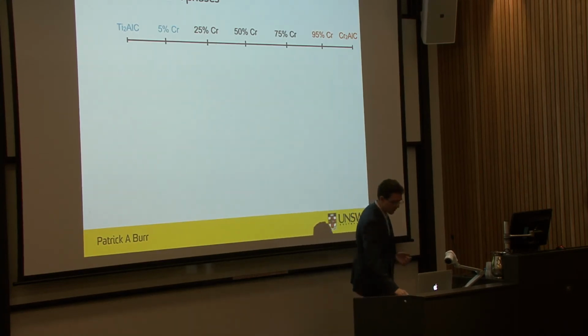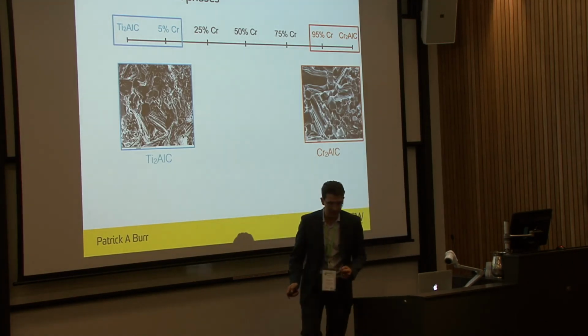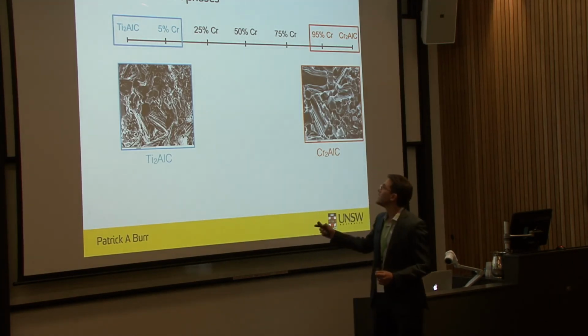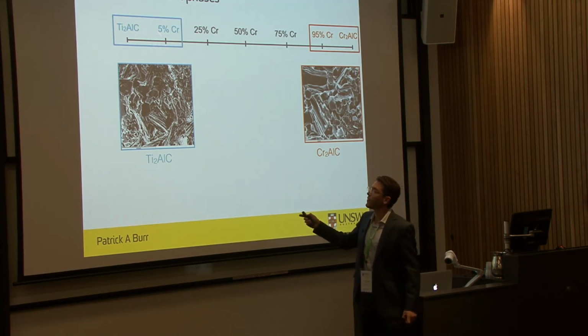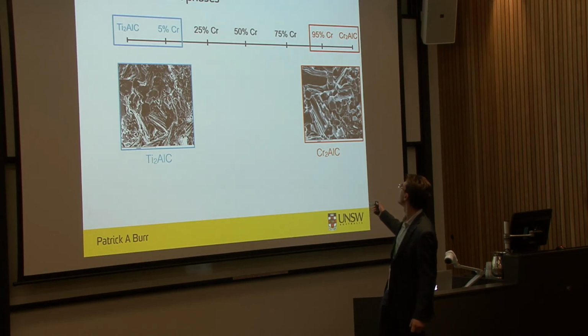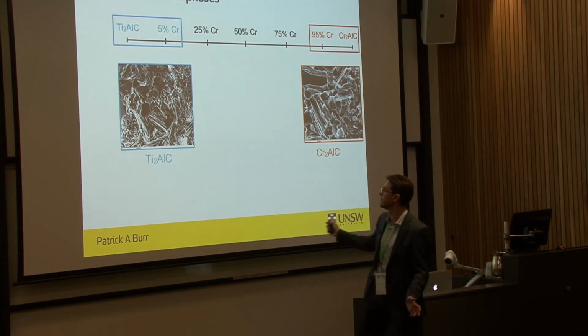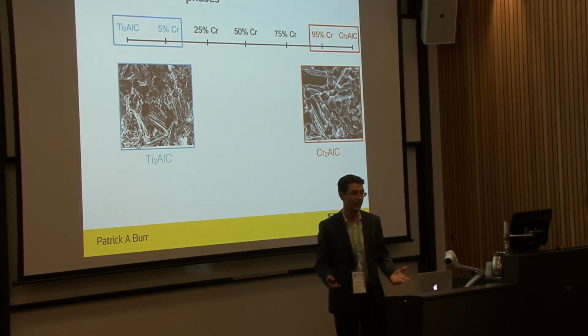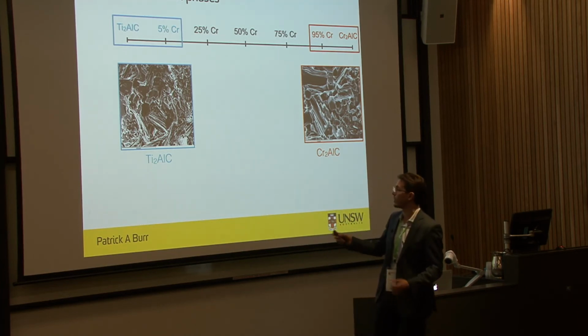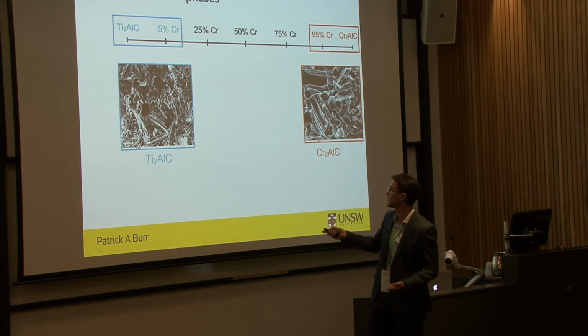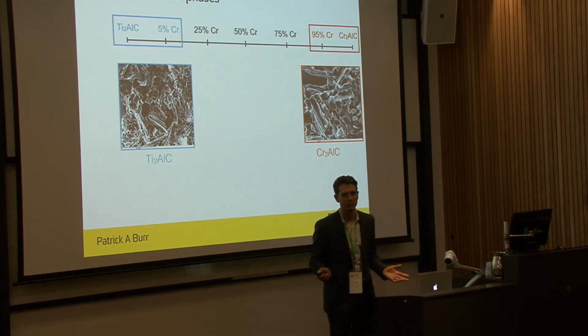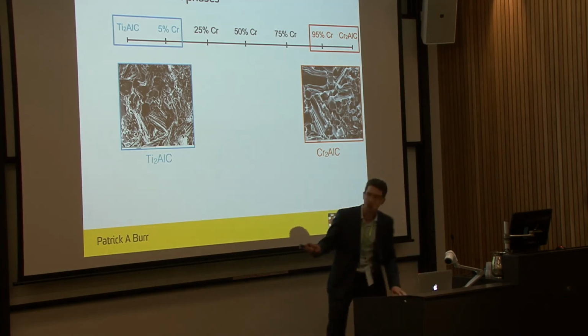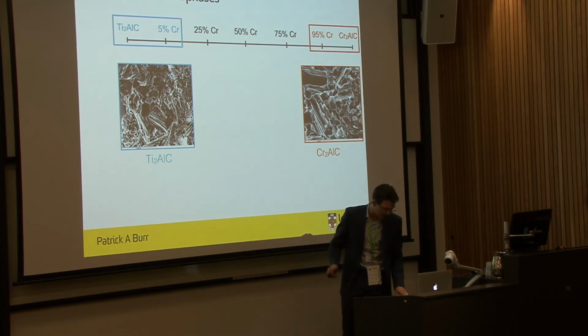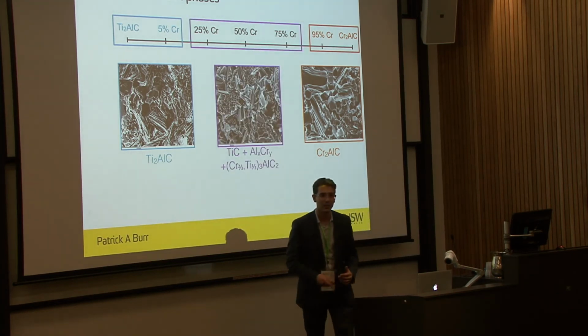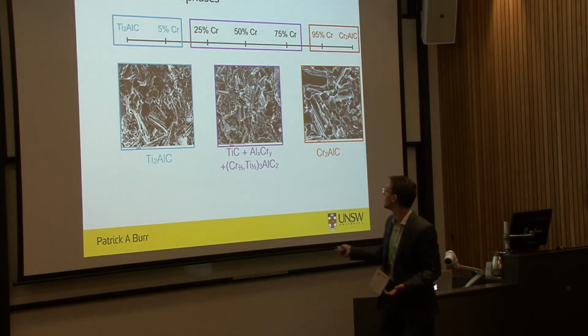So we tried to make a mixture, and unfortunately, at the very end, so adding very little chromium to titanium aluminum carbide, or very little titanium to chromium aluminum carbide, actually gives you lovely single-phase MAX phases. And this is the typical diagram of the cleaved surface, and you can see this laminar structure, and they're actually rather beautiful structures. But as soon as we tried to mix more than that, we didn't get what we wanted. We didn't get a single MAX phase. We got a whole bunch of other things.